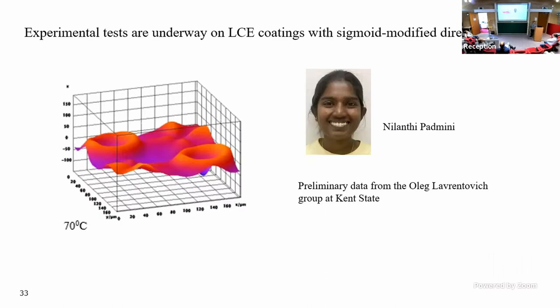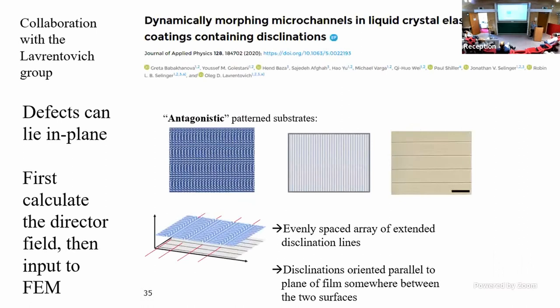I think I'm gonna just mention one work we have done that is published. We considered a case with antagonistic pattern substrate, where one substrate just has uniform planar anchoring and the other one has the director just rotating along the x-axis. If you put those two things together, put the liquid crystal inside, the material forms an array of parallel line disclinations, and they are identical to each other and they're evenly spaced. They're not exactly halfway between the two substrates. Their location depends on the elastic constants of the material, twist, splay, and bend. So they'll be a little closer to one side or the other. But when you cross-link this material, you're cross-linking in those disclinations in the pattern.